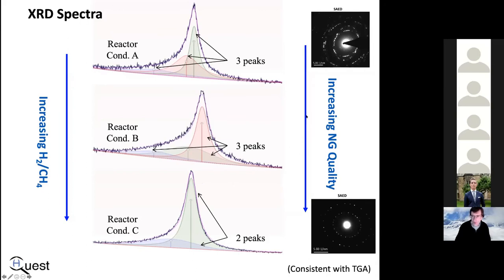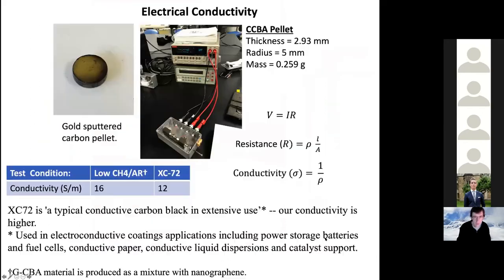In terms of the selected area electron diffraction, with increasing hydrogen to methane ratio, not only does the phase fraction, that is to say the content of nanographene, increase, but so too does the quality. And you can see that by the selected area electron images shown left, and upper and lower on the right. As I made mention, we have sometimes referred to this material produced by the microwave plasma decomposition as a conductive carbon black, not just a graphitic carbon black. The reason for the conductive acronym as well is that we performed, not surprisingly, electrical conductivity measurements, given it would be suitable as electrode material.